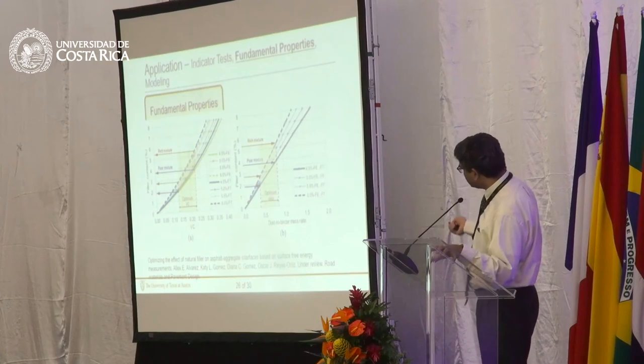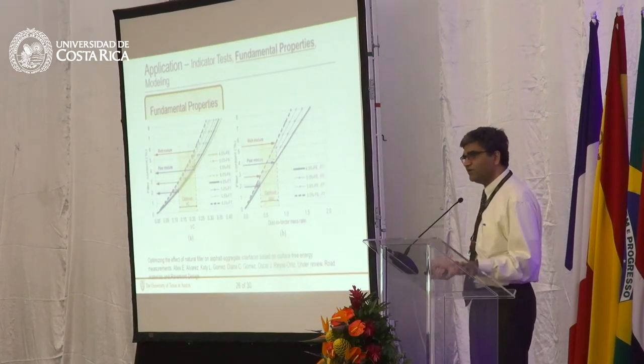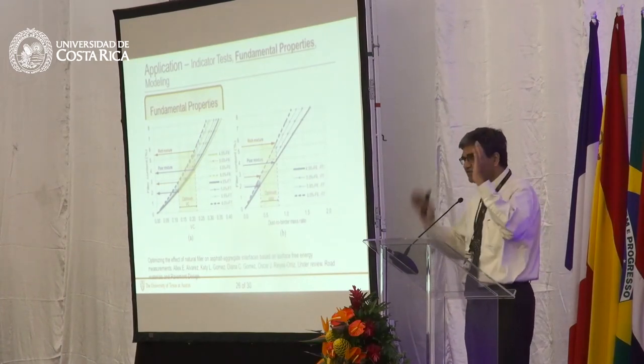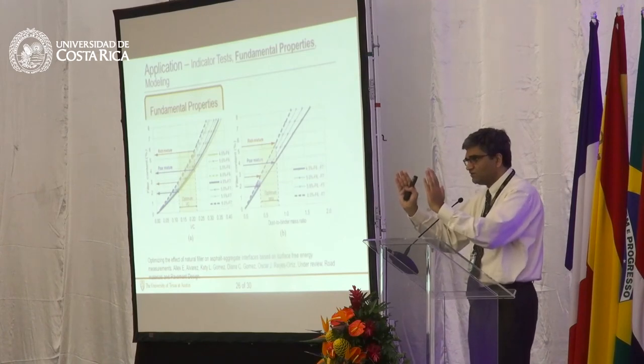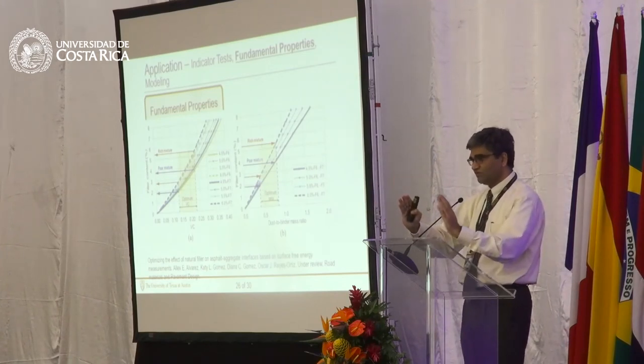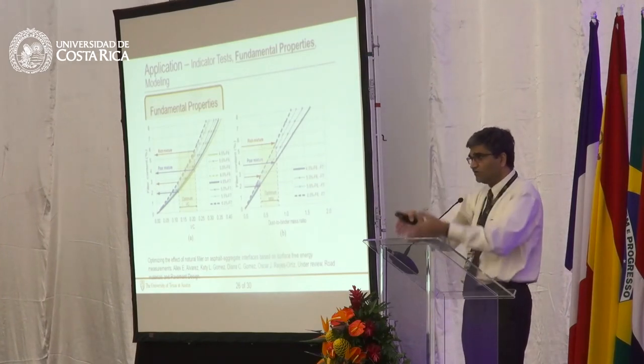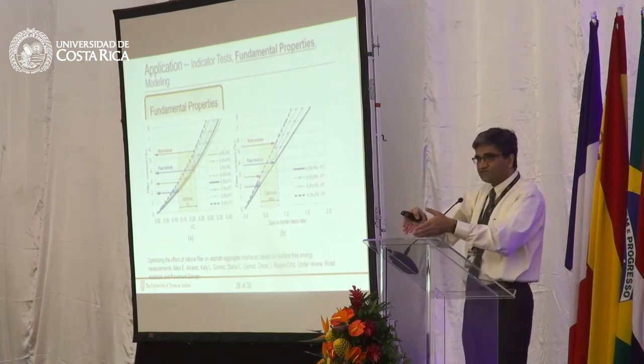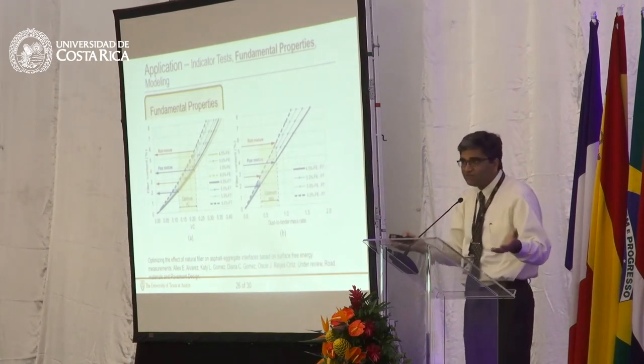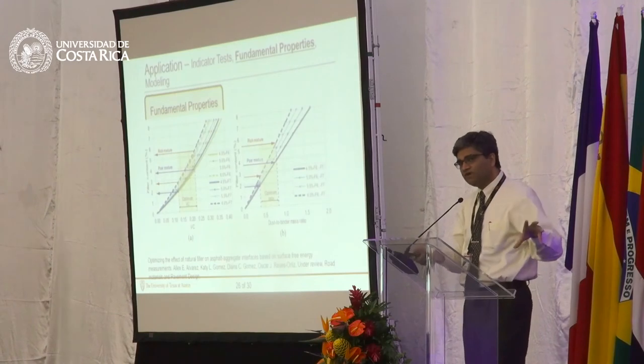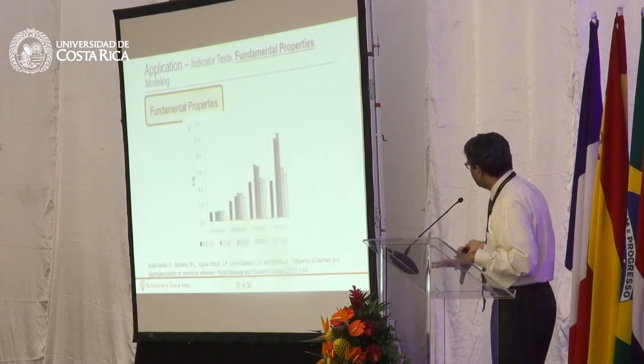Where he combines this result with other mechanical properties and shows that this study gives you this optimum range, this study gives you this optimum range, moisture damage gives you this optimum range. So you can combine all these optimums and find out the slice of dust to binder ratio that you can use. Again, this is a practical tool based on very fundamental knowledge, a fundamental approach, and so forth.